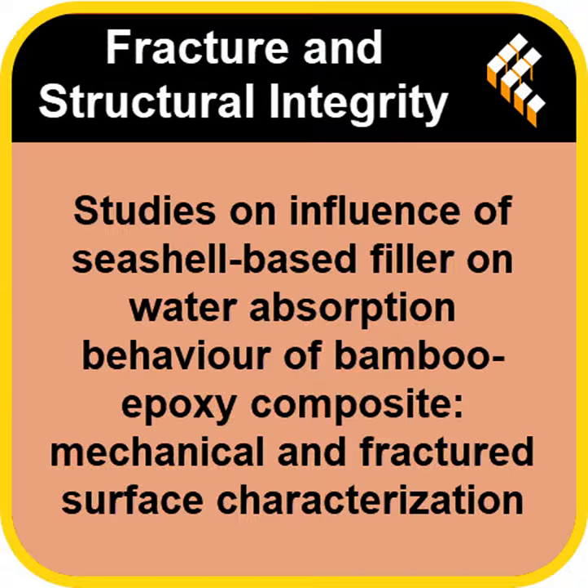It was exactly what you'd expect given the poor performance. The micrographs showed clear signs of moisture damage. The matrix looked degraded. You could see where the fibers had obviously swollen up. And there were large gaps around the fibers, indicating debonding. Lots of evidence of fibers just being pulled right out of the matrix rather than breaking with it. So total failure of adhesion. Looks rough and messy, I bet. Very much so. A clear picture of poor load transfer because the water just destroyed that interface.